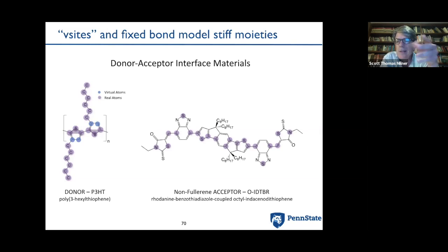Because this thing is basically a rigid pentagon, we know where the blue atoms are if we know where the purple atoms are, and so we don't have to do separate equations of motion for those blue atoms. Furthermore, we know that ring's pretty rigid, so we can fix the bond lengths between the sulfur and the carbon, and even the distance between the 2 carbons across the ring, again reducing the number of high frequency degrees of freedom and allowing us to take a somewhat larger time step.